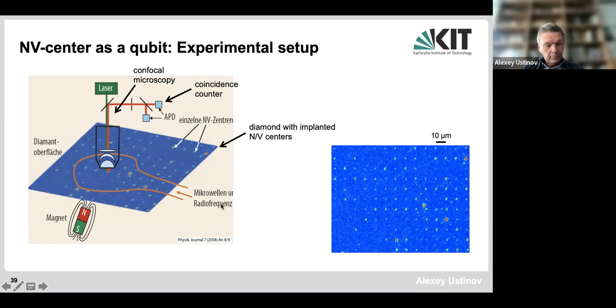On the picture on the right, you see actually the defects which were implanted using the focused nitrogen ion beam, and then annealed, and then you see here that individual defects show a fluorescent response. You can control this, of course, by microwaves, as I said, and also by magnetic field. I should mention that pioneers of this field were 2 physicists from Stuttgart. This is Jörg Wrachtrup and Fyodor Zhelezko, a scientist who is now a professor in Ulm, and he comes from Belarus by his education, and has been working in Germany for many years.